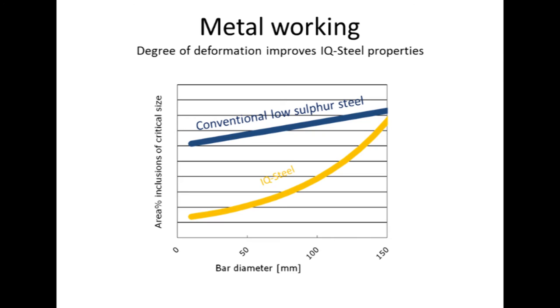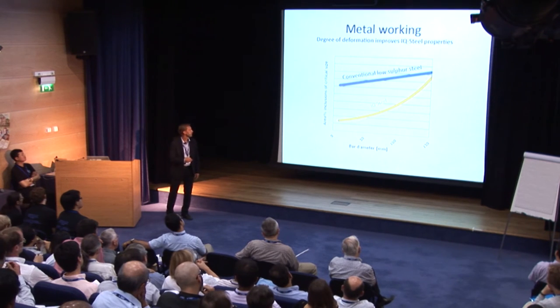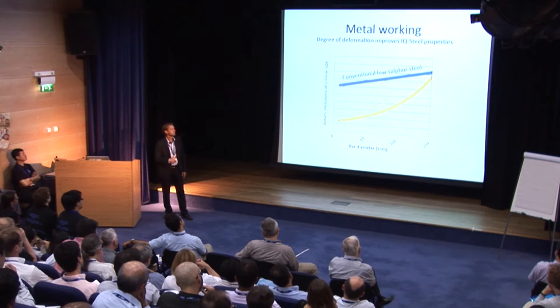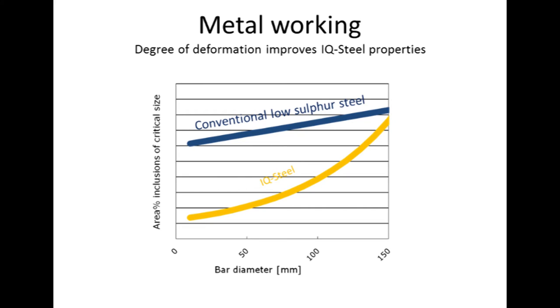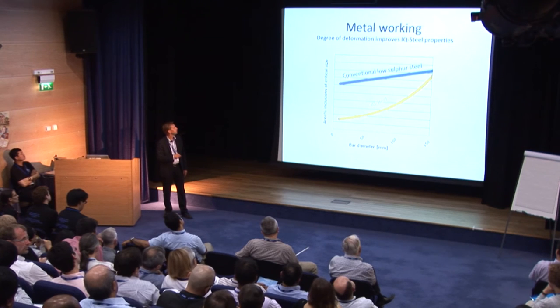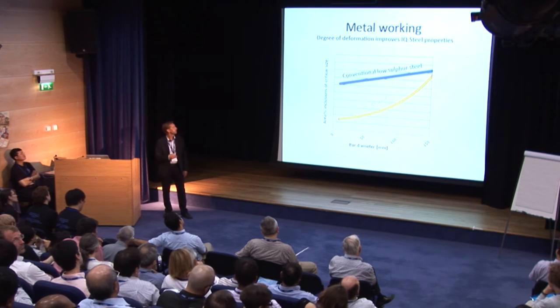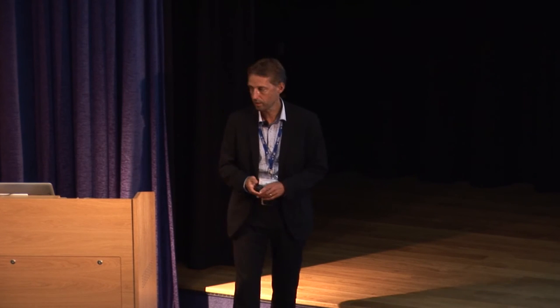And then understanding this, we also have to connect it to the degree of reduction, because that has another aspect. If you start to deform the material, the area fraction of the large size inclusions, the ones that will cause the fatigue, will reduce, because they will be smaller and not detrimental anymore. Whereas more conventional steels are less prone to this. So we have to work with that. And it's possible to make quite significant improvements.